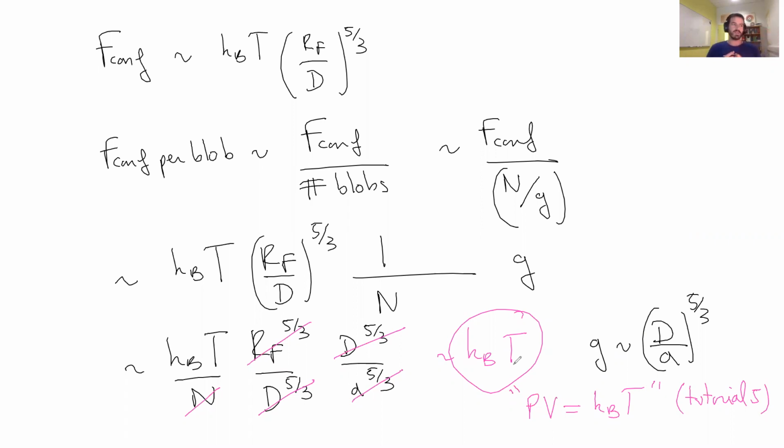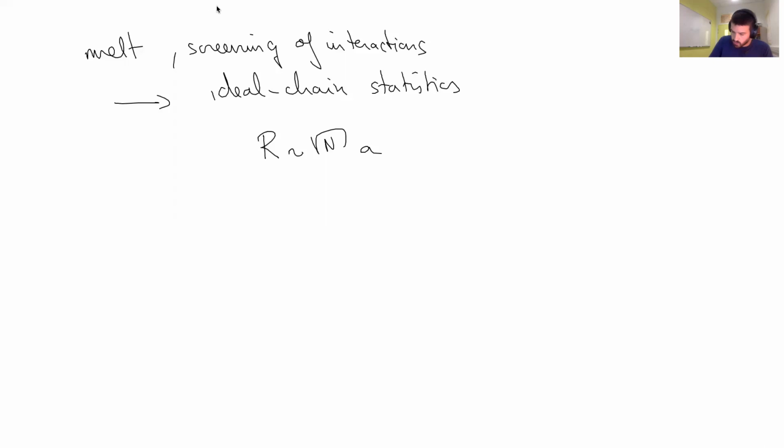Now that we have blobs, and they define inside this, the physics is independent of any confinement. So inside a blob, you should have kbt. You have a chain, and it doesn't matter on the number of objects. You have kbt per blob. Okay, so that's a very important result, and in fact, this is the one you want to remember.